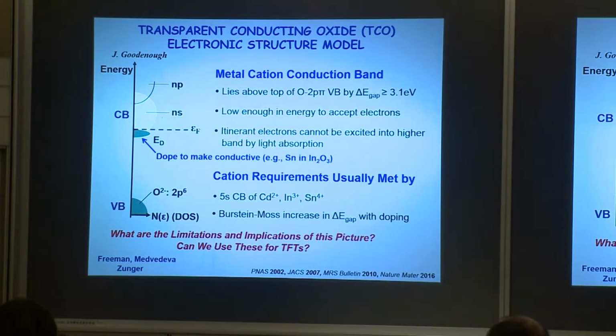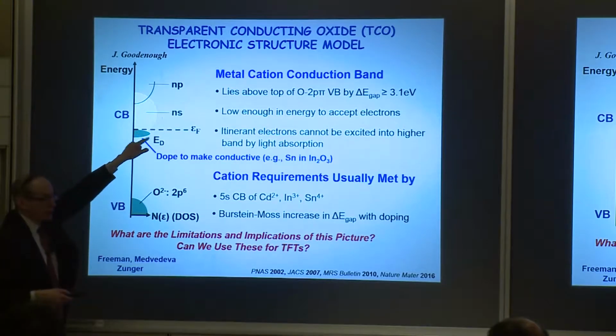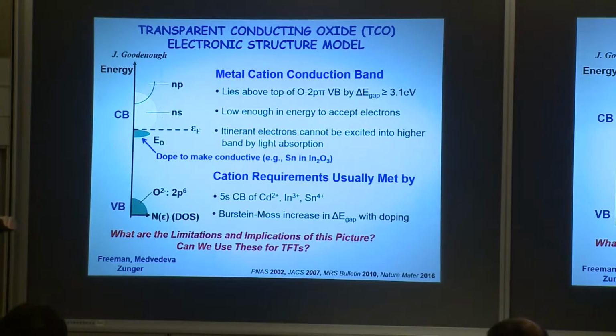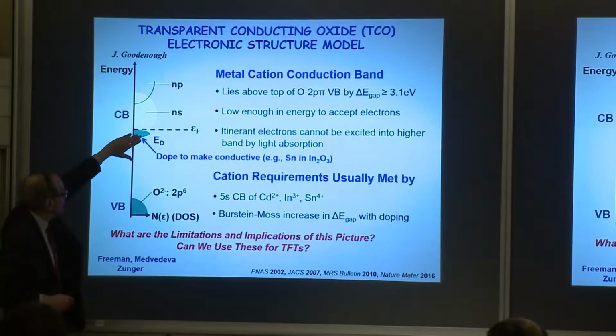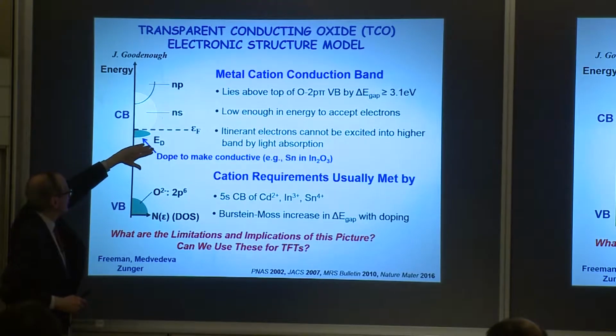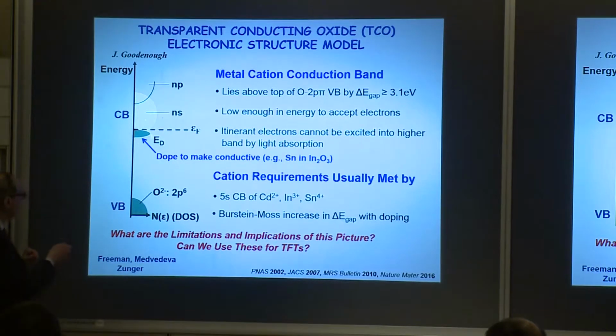So you say, well, what's so special about S states? Well, they're spherically symmetrical. If you bend them around in different ways, the spheres still touch, and you still have a band structure. If I take that indium oxide and dope it with tin, I can make a conductor, a heavily degenerately doped semiconductor. We're not going to do that. For a transistor, we don't want this. For our contacts, we want that. But in both cases, we want this band gap to be large, and you can compute that now, and oxides tend to have large band gaps here, and any states above that, you also want to have a large gap.